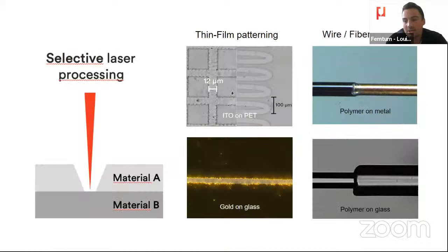Another set of applications, and thanks, Jose, for giving a nice talk earlier about this. We can do selective laser processing. And basically for thin film patterning, it happens that a lot of thin films have very strong absorption bands in the mid-IR. And we can really selectively ablate one layer on top of the other without fragilizing the PET substrate, the glass substrate, the silicon substrate. We have done gold on glass as well. So metallic thin films can be patterned as well.